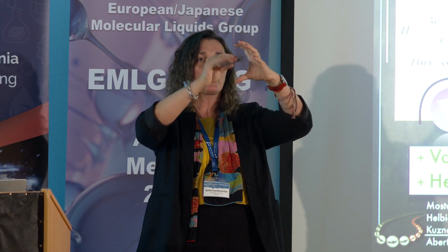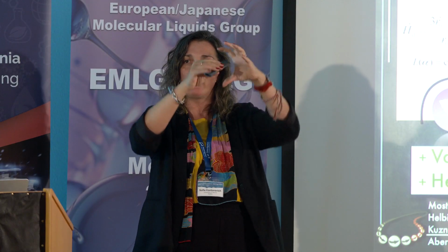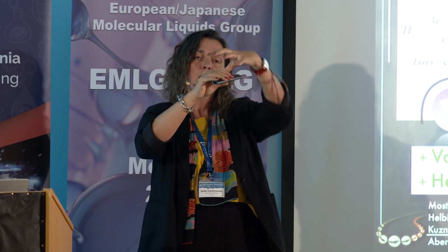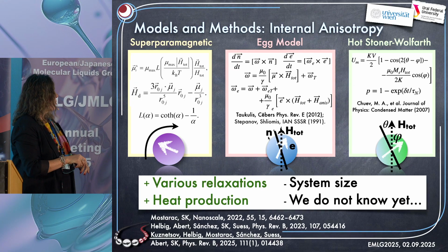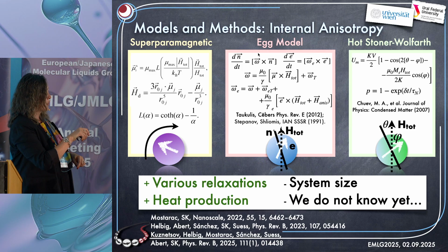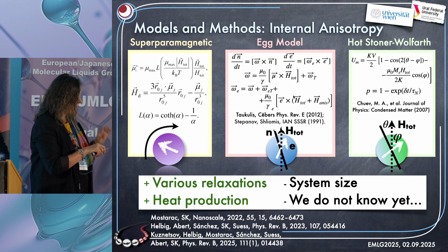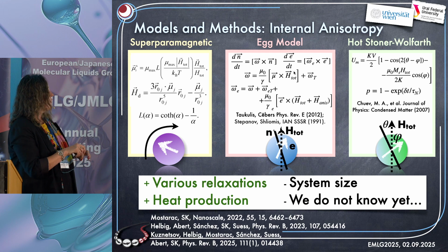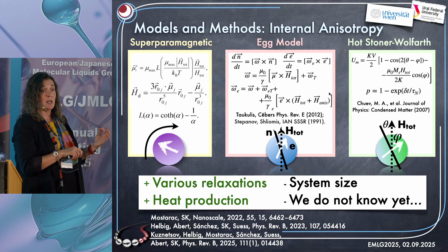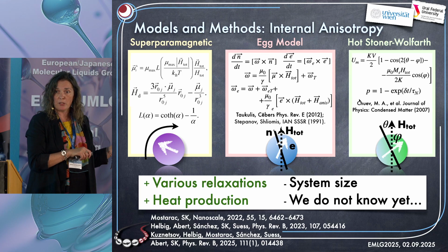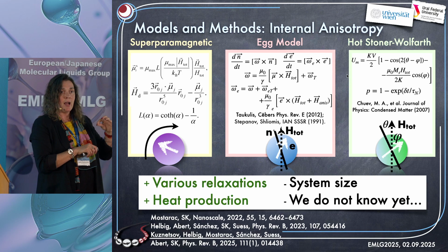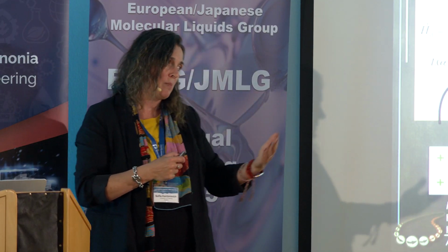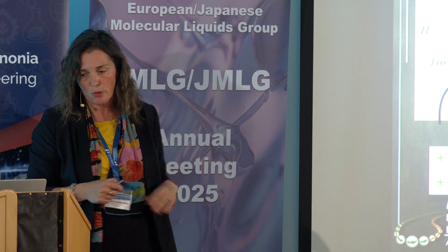And the yellow part is rotating with friction, with viscous friction inside. So this is a moment, and the whole particle is an egg. And in this situation, what you have is really an accurate solution of the Landau-Lifshitz-Gilbert equation, so you get very accurate magnetization dynamics. Of course, you need to go to the time step that resolves the Landau-Lifshitz-Gilbert time step, right? Or you update, so you do a combined step, so not exactly the same step for molecular dynamics and the solution of Landau-Lifshitz-Gilbert.